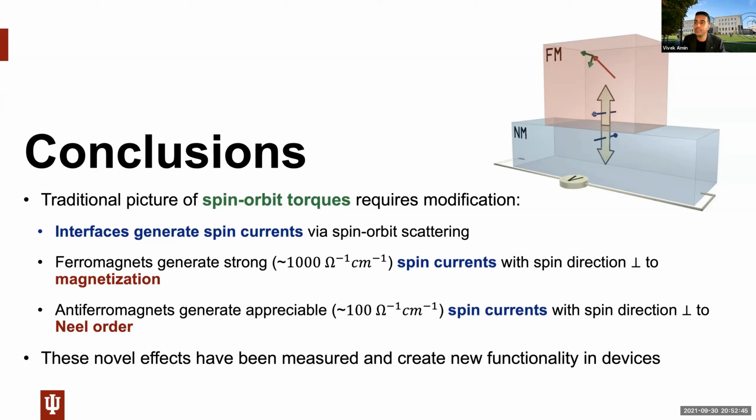So essentially this gives you an effective relaxation time in your calculation. And what you find is that as you increase that disorder strength, the spin currents reduce in value, like say, they may go to half. I don't know the numbers off the top of my head, but they don't die away. So essentially what that tells us is, yes, disorder does affect these calculations, but it doesn't necessarily destroy the effect.